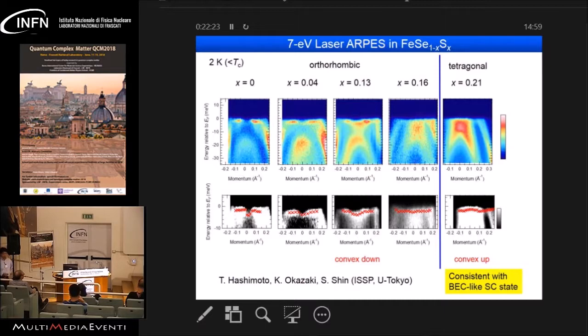Now, my colleague, Professor Shin's group, have measured the 7 eV laser ARPES in this system at 2 Kelvin, which is below the TC, in the superconducting state. The overall feature is shown like this, and it has a very flat dispersion. They are looking at near the gamma point. In the normal state, we have a single hole band near the gamma point. But in the superconducting state, we have a very flat dispersion like this.